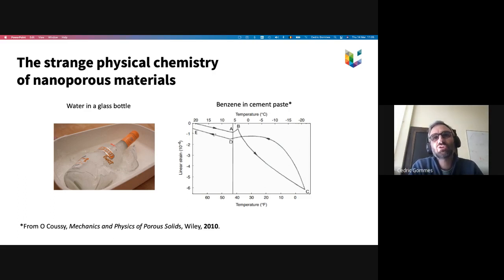But these experiments are concerned with cement paste, which is a nanoporous material with pore size typically ranging from 1 nanometer to 100 nanometers, and with the pores being filled with benzene. What is plotted here is the linear strain as a function of temperature. Decreasing the temperature, you initially see the material shrinking just because this is thermal contraction. And the interesting thing is this part here. You see that the material swells macroscopically despite benzene itself shrinking. And this is a typical phenomenon that you can only observe in disordered nanoporous material.